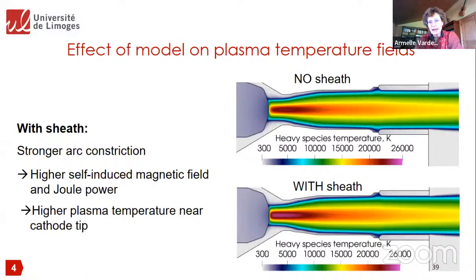If we look at the field, for example the plasma temperature field, we also have some difference in the two fields. As we have a higher constriction with the sheath model, we will get a higher self-induced magnetic field and Joule power, and so a higher plasma temperature near the cathode tip. Is it important for the prediction?